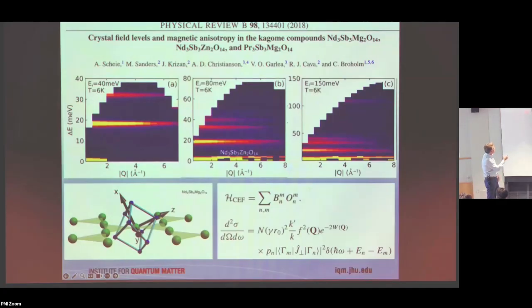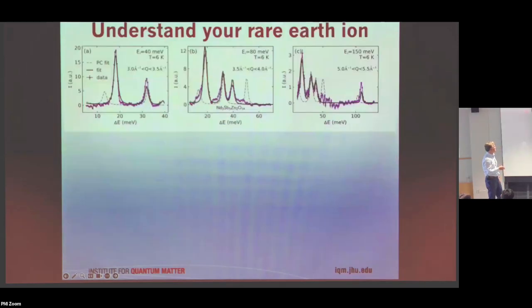These lines here are excitations that maintain the spin-orbital quantum number, but the way that spin and orbital degrees of freedom are entangled is different in each of these levels. The neutron can make transitions between those levels. Here we just use different incident neutron kinetic energies, 40, 80, and 150 meV. It's the same material and the same spectrum, but we're able to see more of the spectrum. It was important to go all the way to 150 to get the highest energy excitation, up to 120 millielectron volts. You could say, why are you doing this high energy stuff if you're interested in the low energy collective physics? It's because I need to know what the ground state multiplet looks like, and that requires looking at all of these levels.